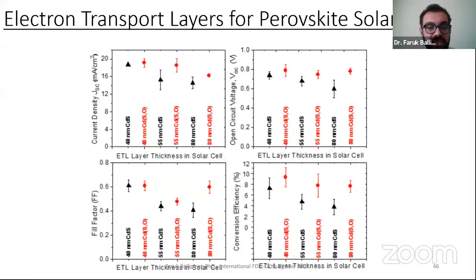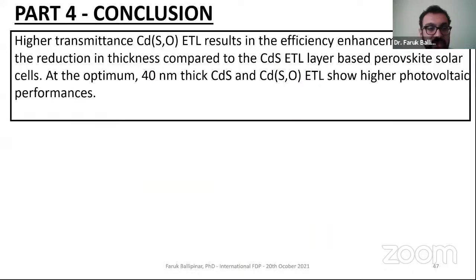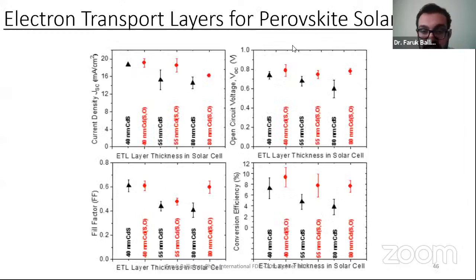In all thicknesses, basically there is an increment in the cadmium oxysulfide based compared to cadmium sulfide based perovskites. But we're actually looking for the optimum thickness as well. So for the optimum thickness, the 40 nanometer thick cadmium sulfide and cadmium oxysulfide show higher efficiencies. Basically we can see from the graph higher efficiencies compared to the others.